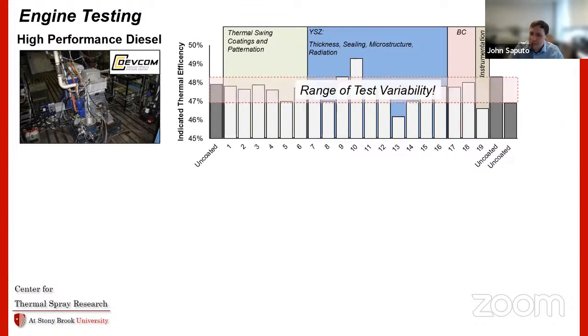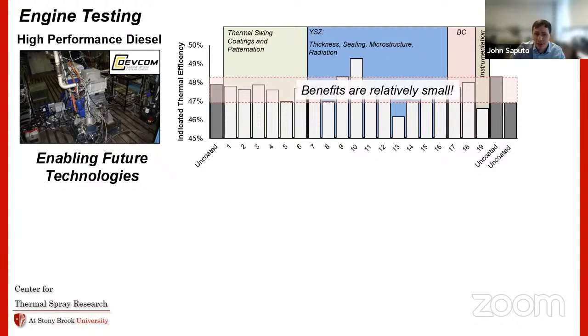And what you end up seeing is that the range of variability in these systems is kind of huge. We're seeing about 47 to 48% change in just the uncoated tests, which is outside of the variation that you're seeing in the tests with all these different TDCs. There are some things that lie outside of that range, some below and some above, but those benefits are rather small. At most they're about 0.5% that you could potentially gain from doing this, but it would be really difficult to get everything tuned exactly right to do that. So instead of getting direct performance benefits from these things, you can go into enabling different technologies.